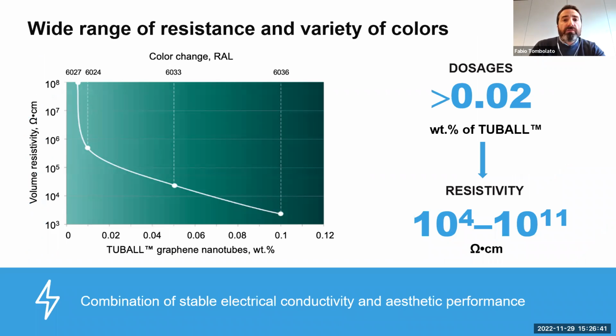Color is an added value that can be reached using graphene nanotubes. As you can see from the table, the very low working dosage of graphene nanotubes as a function of the target volume resistivity leads to the possibility to develop colored products that bring together electrical conductivity and aesthetic performances.